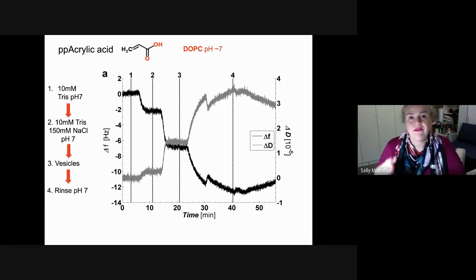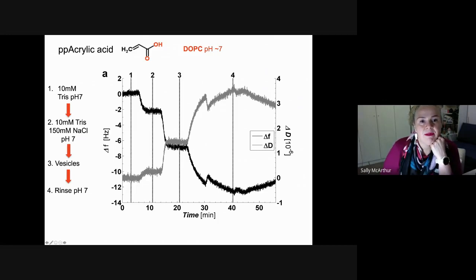At pH 7, so we've taken our acrylic acid surface, we're in the QCM, we've got a flow cell, and we're flowing lipid vesicles over the top of the surface at pH 7. And you can see we expose the surface to pH 7 here at this point 1, and this is just the solution. So we can see that this is the frequency change. When we see a drop in frequency, that means we've added mass onto the surface. If we see a change in the dissipation, that's measuring the viscoelastic properties of our surface. So the interesting thing is at pH 7, just in this buffer, you add mass, and that's because you've actually added a little bit of swelling on the layer.